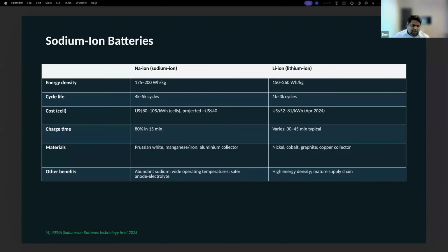In terms of the cathodes of sodium-ion batteries, they use layered oxides, polyanionic compounds, and Prussian blue analogs, which avoid nickel and cobalt. As I mentioned before, nickel and cobalt are predominantly deposited in the Democratic Republic of Congo, and it's one of the highest costs in the battery chemistry. So researchers are trying to find ways to reduce the overall usage of nickel and cobalt in battery chemistry, and sodium ion is proving to be a good alternative for that approach.